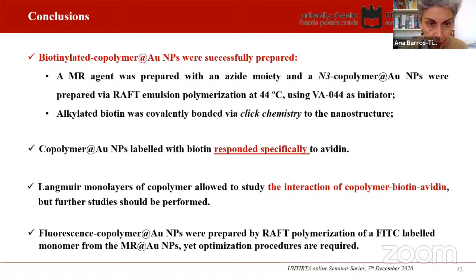The biotinylated copolymer anchored at gold nanoparticles were then successfully prepared. The macro raft agent was prepared using this azide, and 44 degrees Celsius was required for the use of the VA044 initiator.